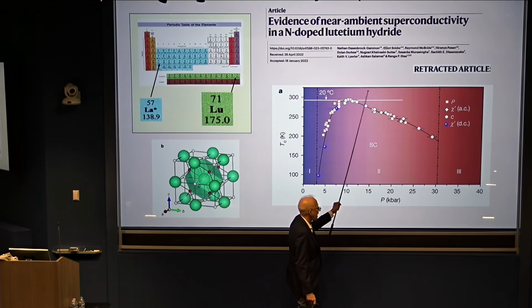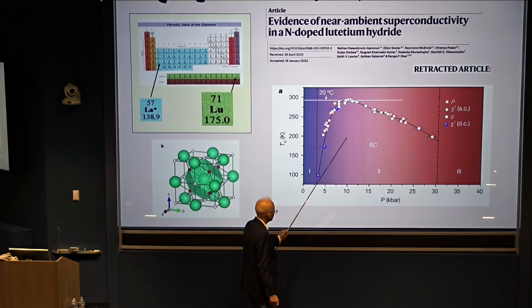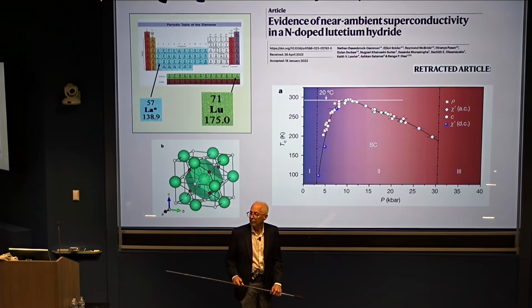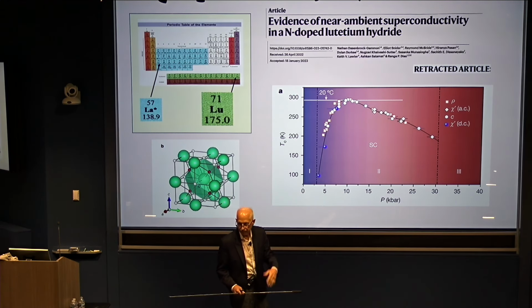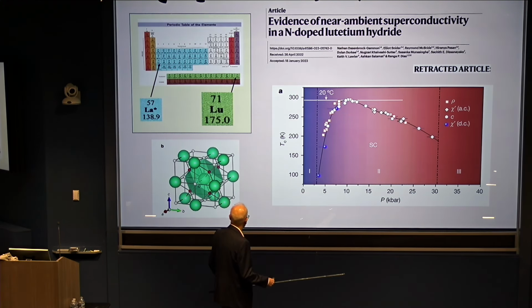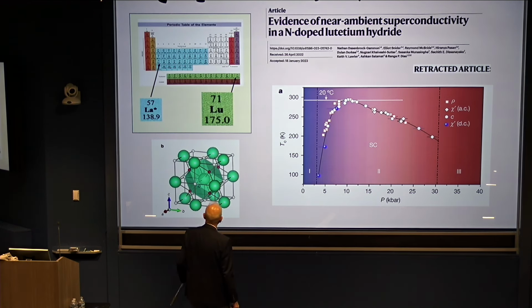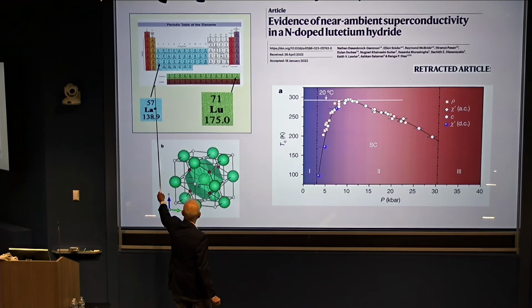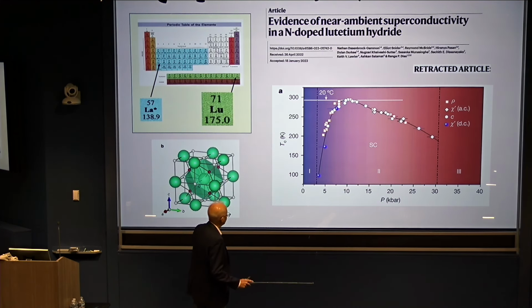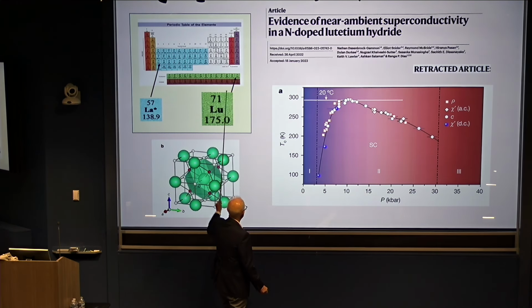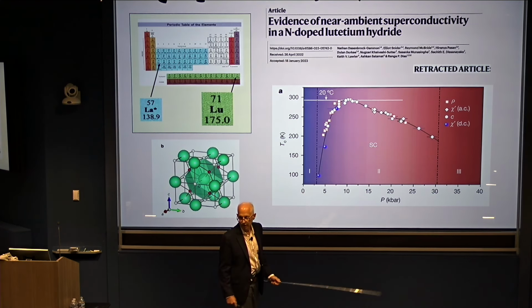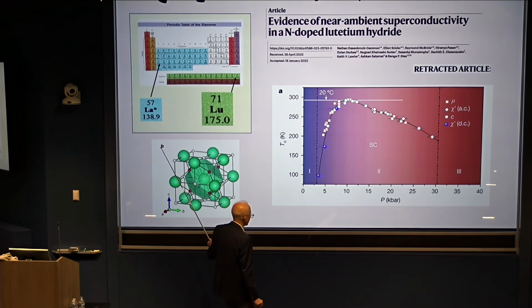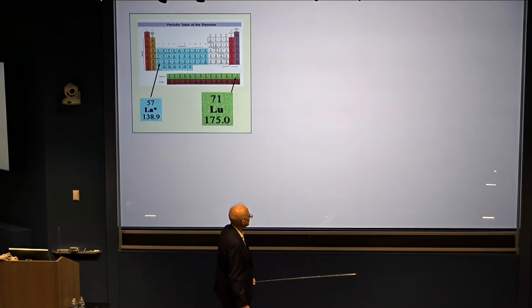Unfortunately, this paper was retracted for a number of reasons that I don't want to get into, but we were still quite interested in whether or not there's something to this phenomenon. So we started to work on this problem. Here's a picture of the model structure. So here we're moving from lanthanum on one end of the rare earth row all the way over to lutetium, where we have all the F electrons filled, and really the question is whether that somehow is affecting the difference in the superconductivity behavior of the hydride of lanthanum versus the hydride of lutetium.